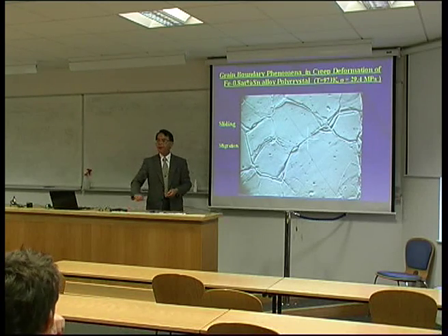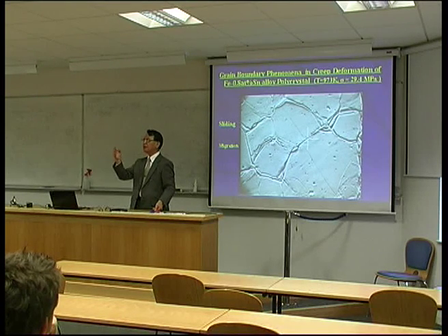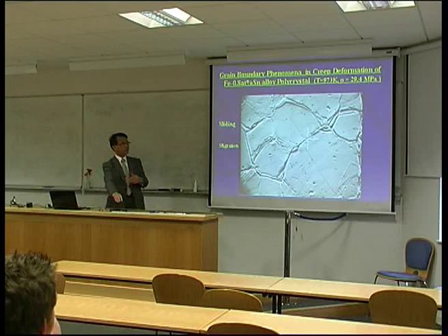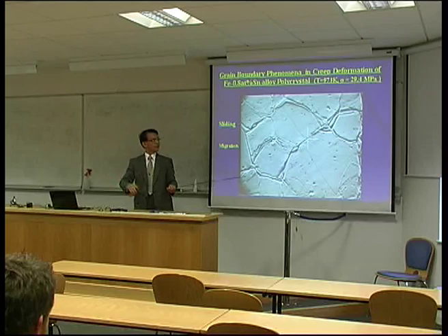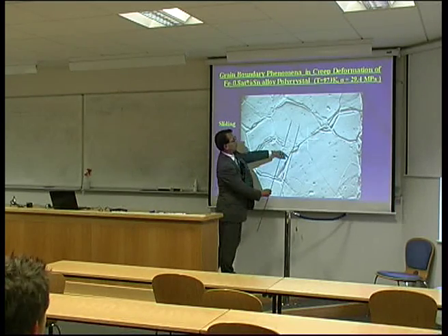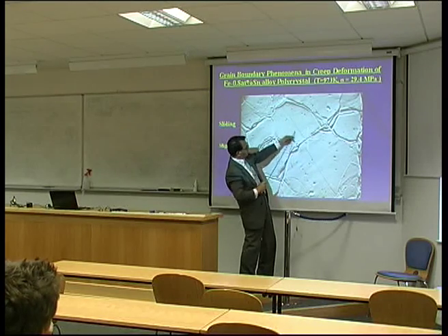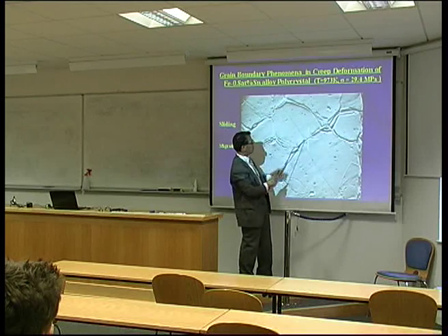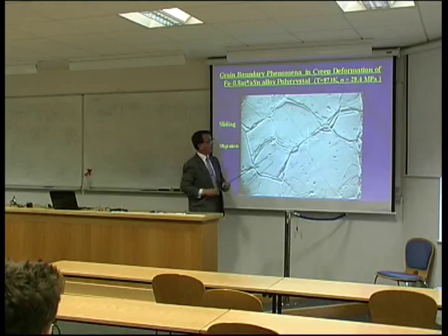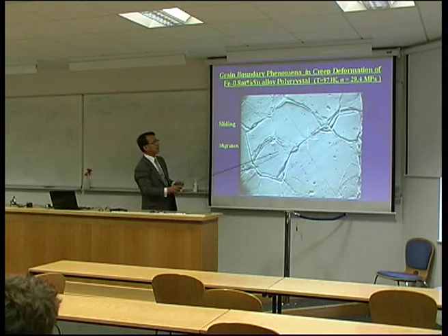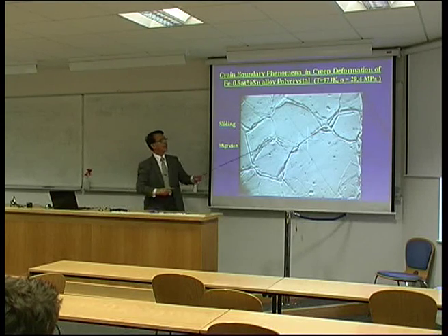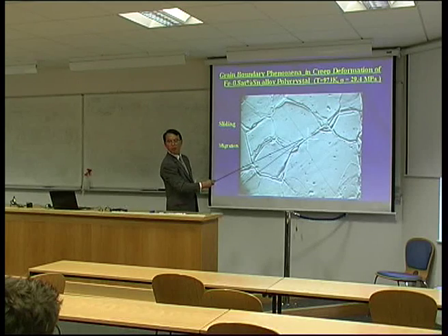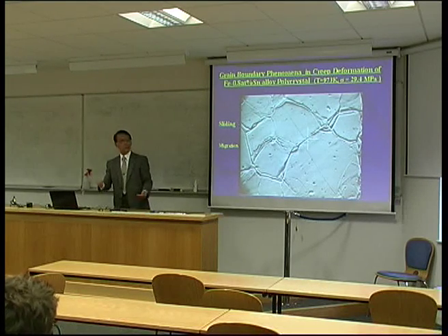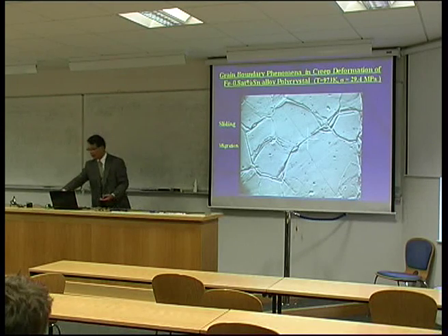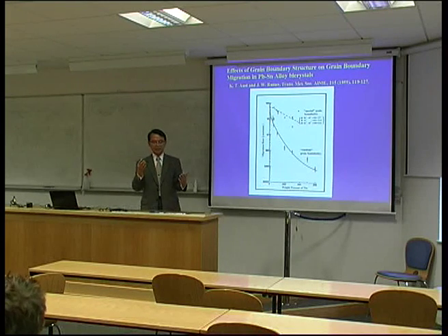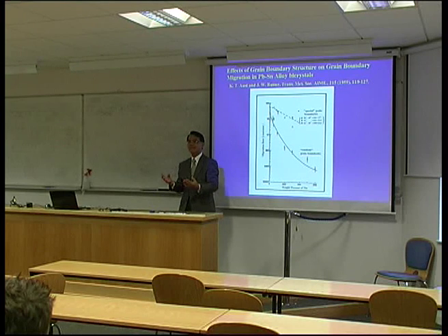For example, when you deform the polycrystalline sample at high temperature, the boundary can play an important role. Sometimes boundary migration can occur under stress, or grain boundary sliding occurs. So this boundary slides relatively, because here the original scratch shifts like this. This means grain boundary sliding occurred. And normally at high temperature deformation, such sliding causes intergranular fracture at the triple junction. So this is very important. And also, the mechanism of superplasticity is based on grain boundary sliding. So to discuss the superplastic mechanism or the fracture mechanism occurring at high temperature, we have to know the grain boundary sliding behavior.